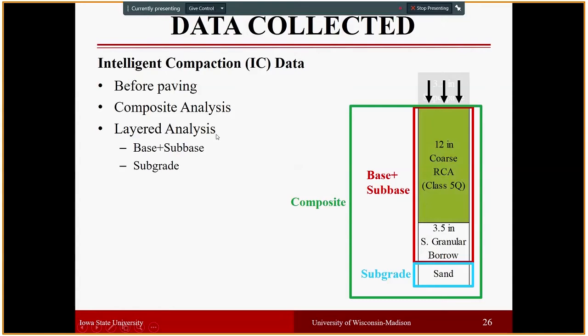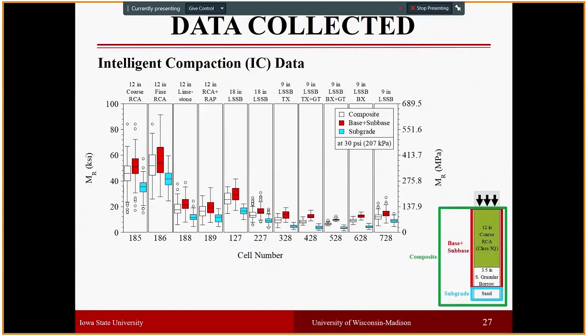In the composite analysis, we assume the entire base, subbase, and subgrade layer as one composite layer. On the other hand, with the layered analysis, we calculated base and subbase stiffness and subgrade stiffness separately from each other. So the composite results are shown in the white boxes, base and subbase in the red boxes, and subgrade resilient modulus data are shown in the blue boxes.